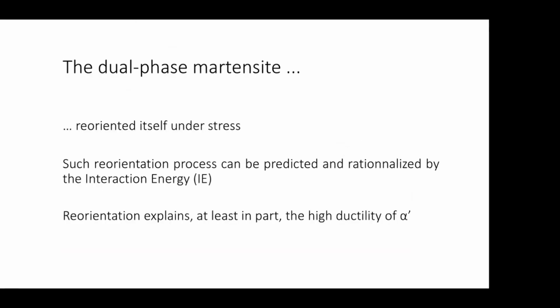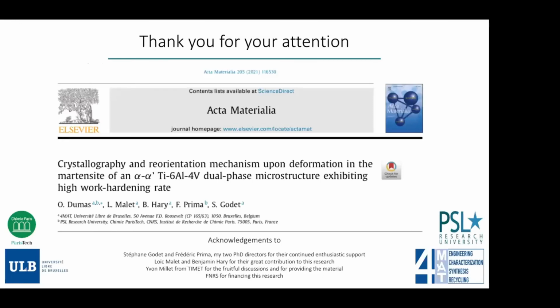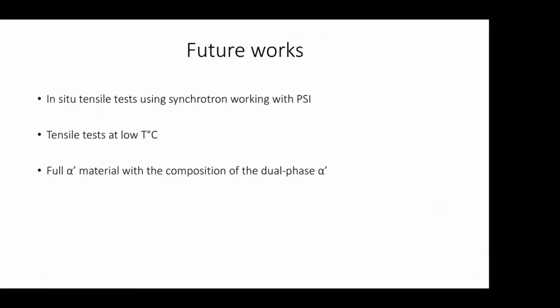And to conclude on this martensite after deformation, I can say that we could find some reorientation in the martensite of TA64. We can also say that we use the interaction energy to rationalize the reorientation, but we can also use it to predict the reorientation. And we think that reorientation can explain, at least in part, the ductility of such a martensite. If you're interested in that work, you can find a bit more of it in the paper, which was written in Acta. So thank you for your attention, and do not hesitate if you have some questions.